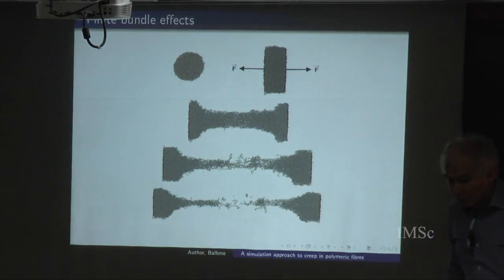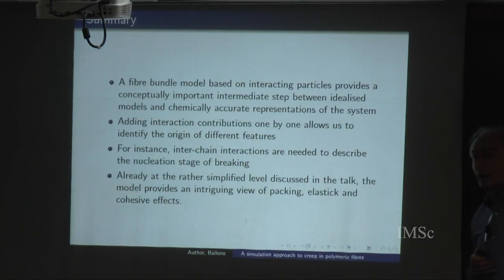If we remove periodic boundary conditions, we have necking. It is much easier, so we do not need to wait for a nucleation event. It immediately starts deforming the surface, and eventually it breaks. Of course, the two processes are in competition. So if we increase the cross-section, as we've seen, there will be an equilibrium or a competition of the two processes. And this is essential for us because we are aiming at nanometric bundles.